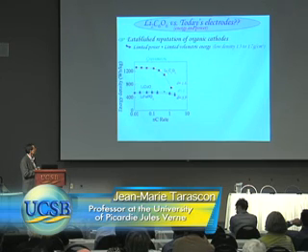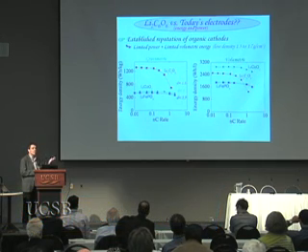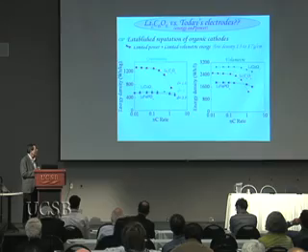you can see that this organic molecule can perform very nicely, with a huge increase in energy density. Of course, if you put this in terms of volumetric density, owing to the fact that the polymers are light compared to inorganic compounds, here the advantage is somewhat decreased. But still, up to 1 C rate, which means in this case you can use this power in 1 hour, you can have nice performances.